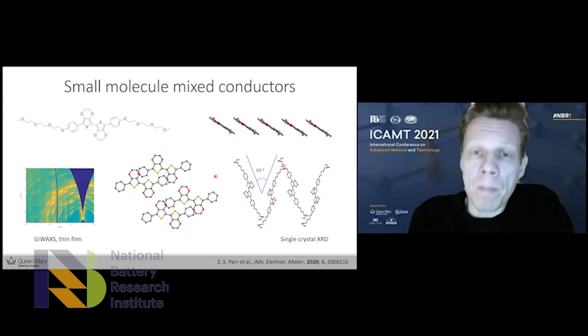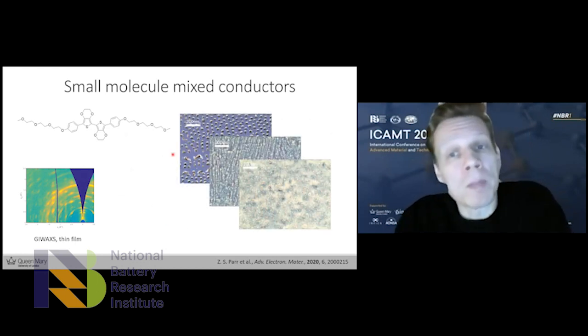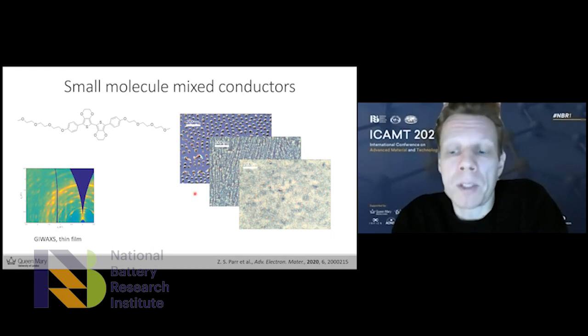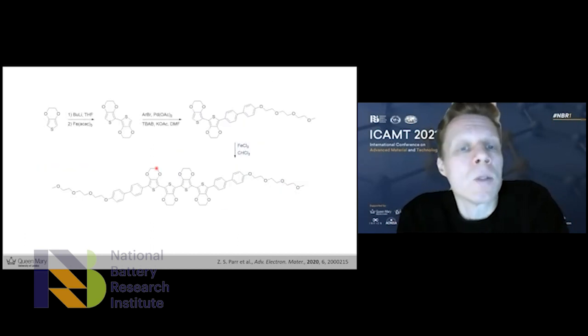So therefore, we went back to the synthetic chemistry lab. Oh, I should mention, we also struggle a lot to get homogeneous films of this material because of the high crystallinity. So the printing process is not very efficient. So we went back to the chemistry lab and tried to see if we could address this from a synthetic chemistry point of view. And what we did was elongate the pi conjugated segment of the molecule.